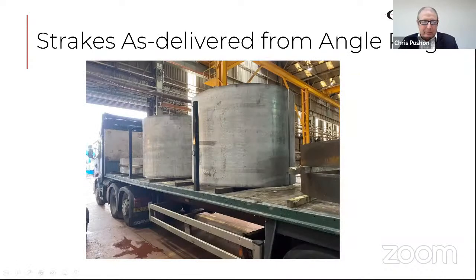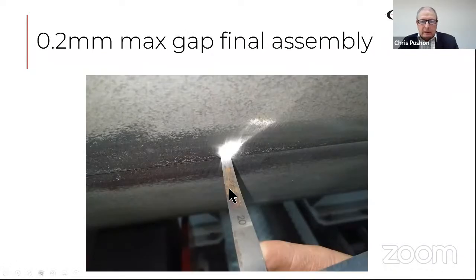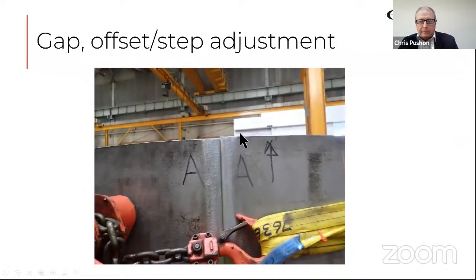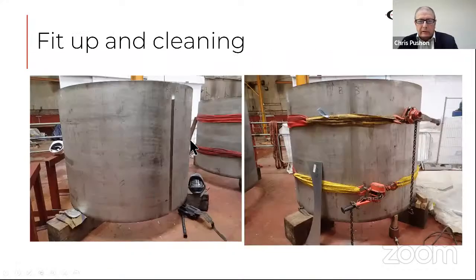So you see the parts, these are the parts arriving on the lorry. One of the big concerns at the start of the project was, could we get the fit up that we required? And our target was about a millimeter. And what we found is we could readily achieve this 0.2 millimeter gap. And what you notice also, it's a very dirty feeler gauge, which I was a bit unhappy about, but it made no difference to the weld quality. The fit wasn't perfect to start with, but with a bit of adjusting, you can improve it. In fact, we started off with a 40 millimeter gap and managed to squeeze it up to 0.2.